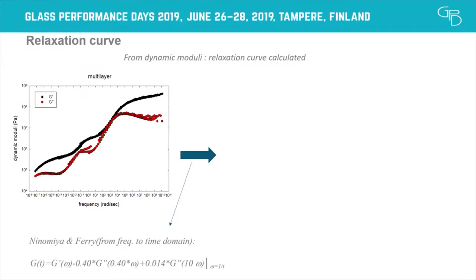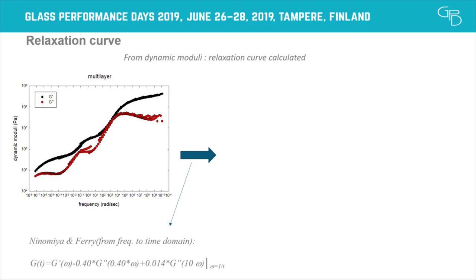Moving from the relaxation curve to the PRONY series: we convert from the frequency domain to the time domain using a standard formula, going from dynamic modulus as a function of frequency to relaxation modulus as a function of time. This nicely shows the two transitions from the two materials, producing a clean curve suitable for calculations.